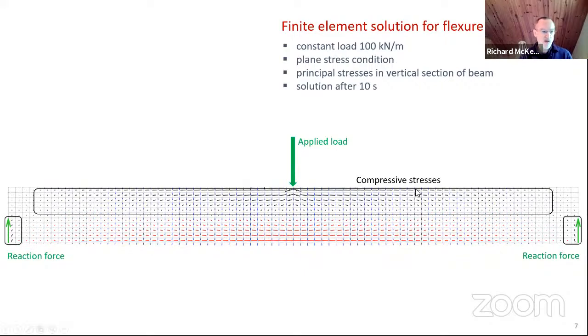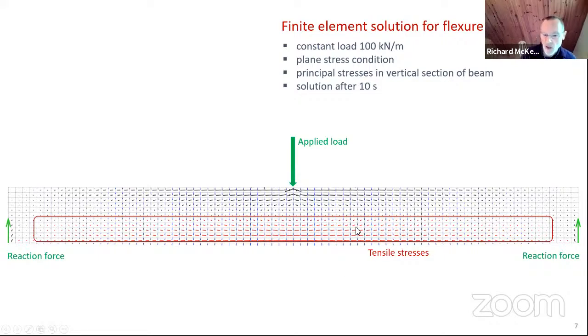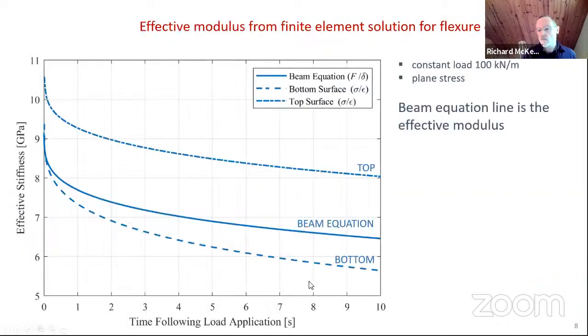There are compressive stresses at the top of the beam and at the reactions on the side. So those are the local effects as a result of the applied loads. We've got tensile stresses in the bottom part of the beam, and I'd emphasize that because of the time dependence in both elasticity and in creep, primary creep and secondary creep, it's not completely symmetric top and bottom. If you had an elastic beam, it would be symmetric. Again, this is a figure that I've shown in the paper. So when you get the paper, you'll see this.